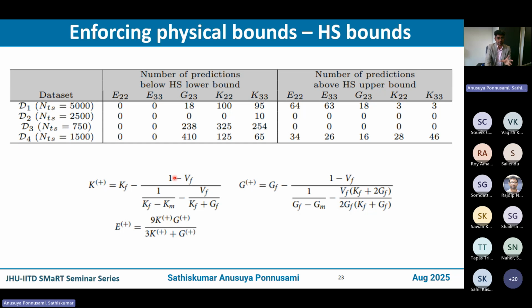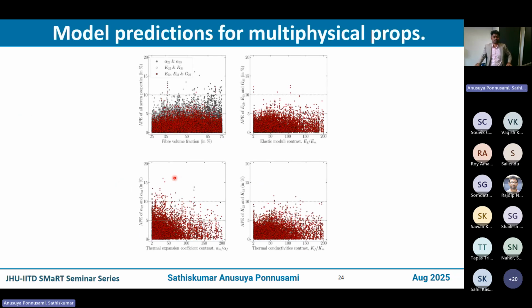Okay, so once you have some sort of physics that is infused, which is quite important in homogenization, these bounds should be met strictly. And some of the results are what you see here in terms of the error metric, absolute percentage error of different properties. But without getting into the details, what you really see here is for the vast majority of the samples, the error is within 5 to 7%.